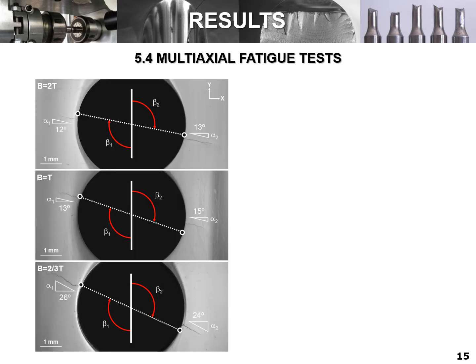Let me show you some results about the multiaxial fatigue campaign. In this slide, we can see the typical crack paths and initiation sites found in the experiments for the different loading scenarios. The fatigue process is characterized by the nucleation of two cracks in diametrically opposite points, whose locations are governed by the BT ratio.